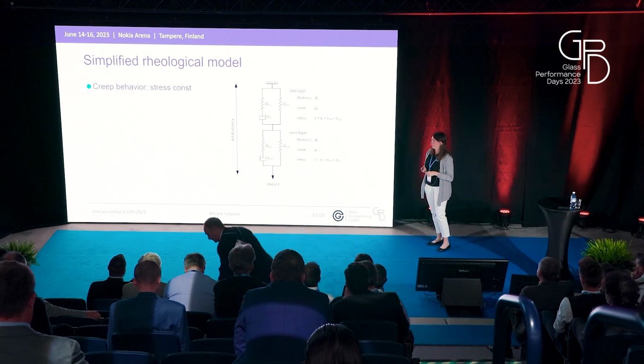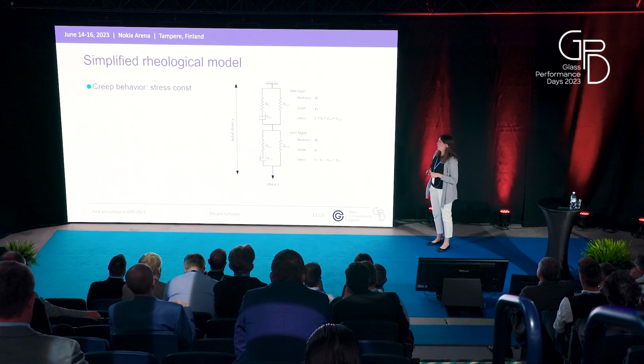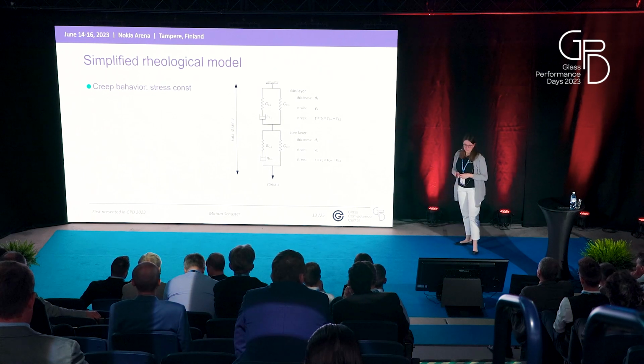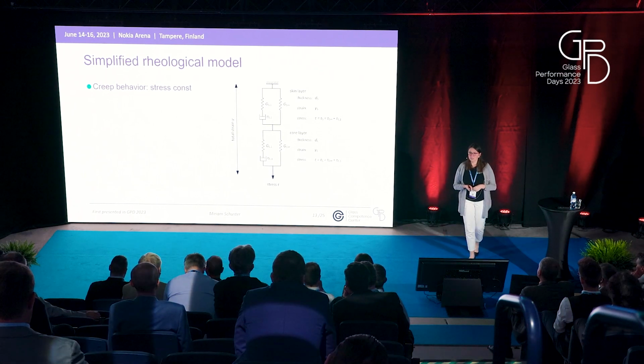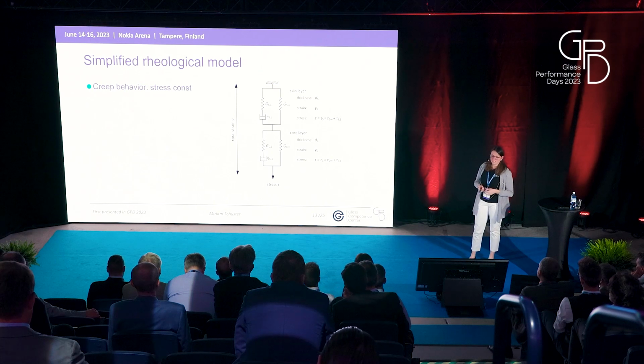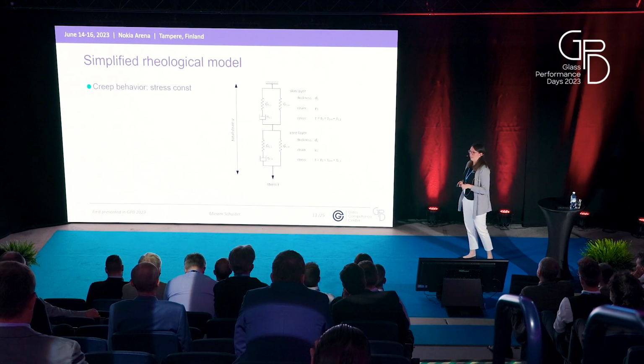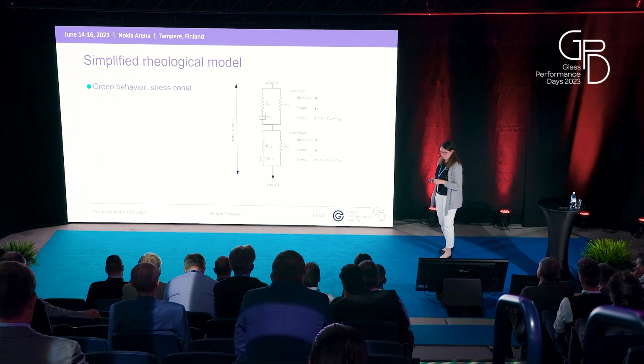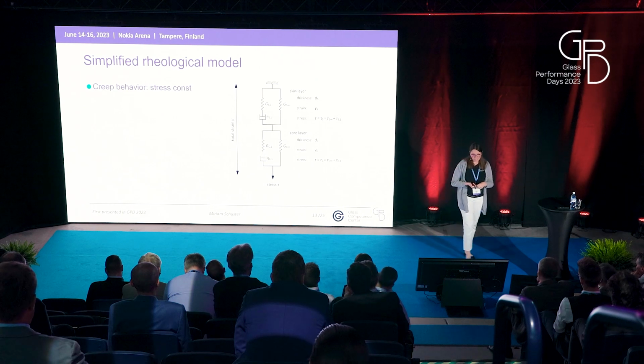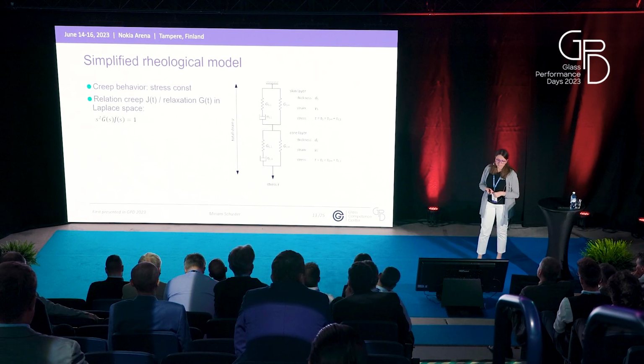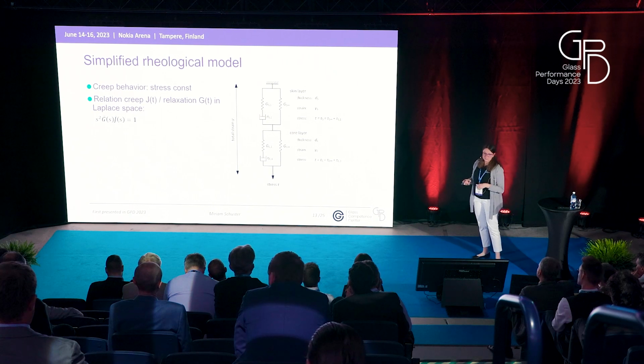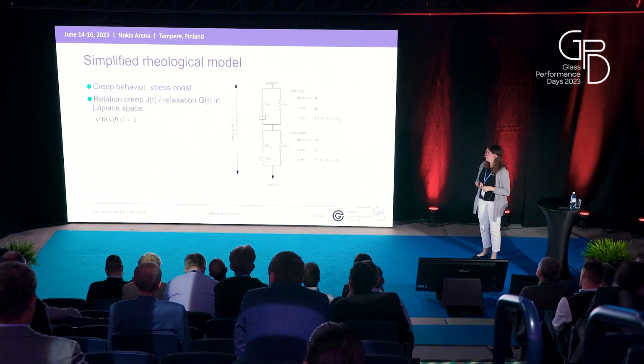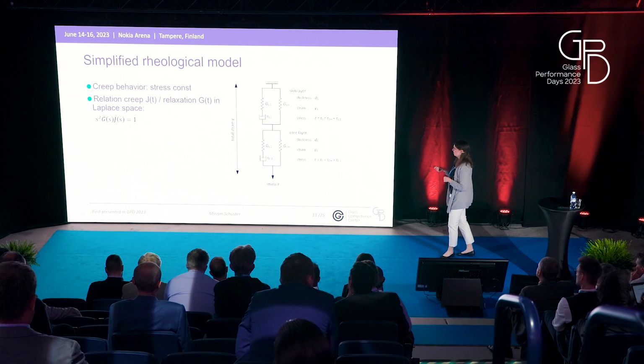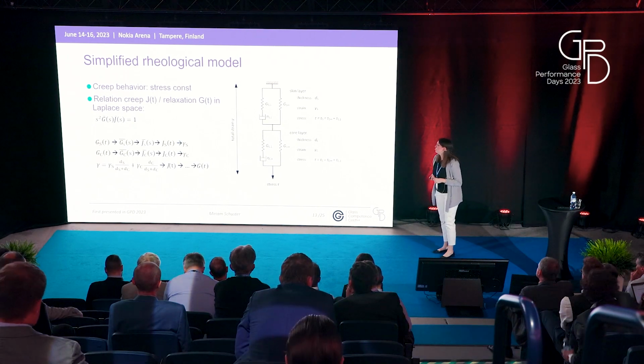So another method to come to the effective shear modulus value of a multi-layer is to consider creep instead of relaxation. And in a creep test, we have the stress which is held constant. However, we do only know our relaxation parameters for the individual layers, since the Prony parameters are relaxation parameters. But we also know that in the Laplace space, there is a simple relation between creep and relaxation, which is depicted here.